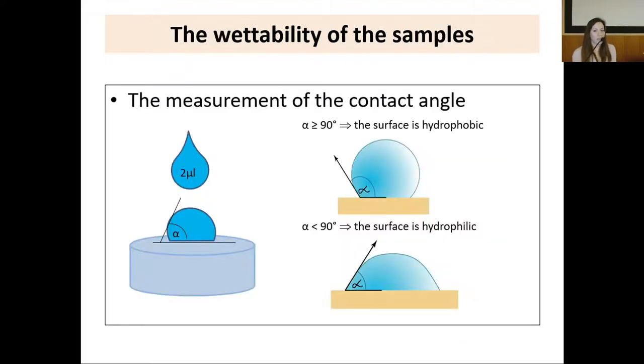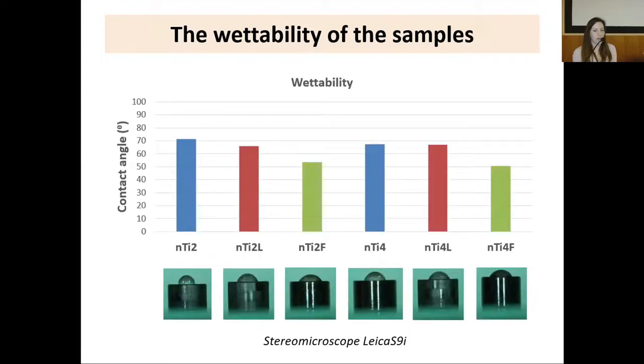The estimation of wettability was performed by measuring the water contact angle using the sessile drop method. If the angle alpha is larger than 90 degrees, the surface is considered hydrophobic; otherwise it is regarded as hydrophilic. According to our measurements, femtosecond laser-treated implants have a smaller contact angle and greater wettability.